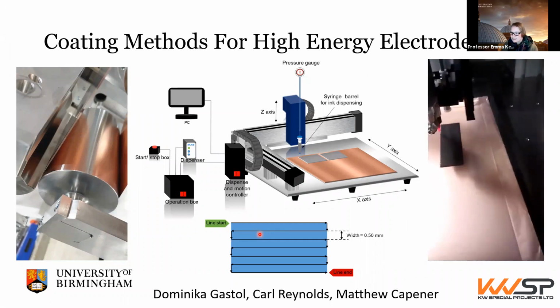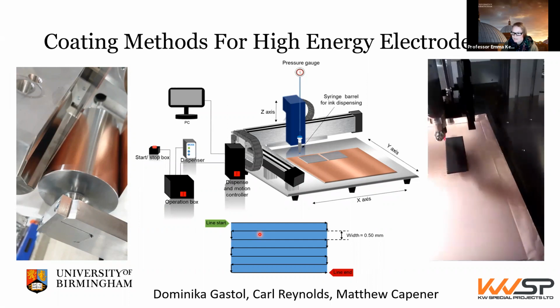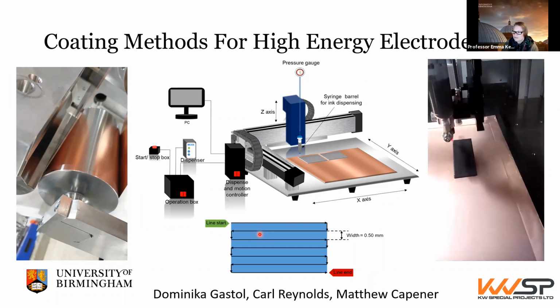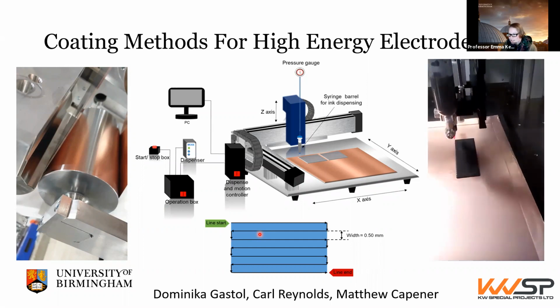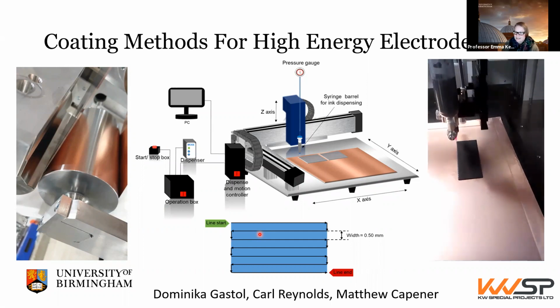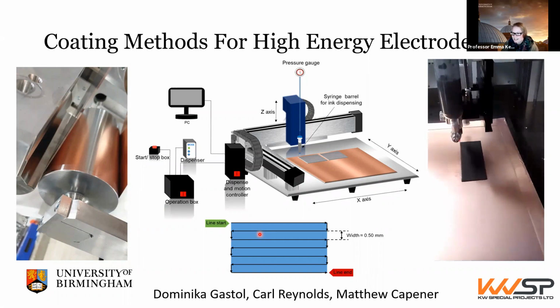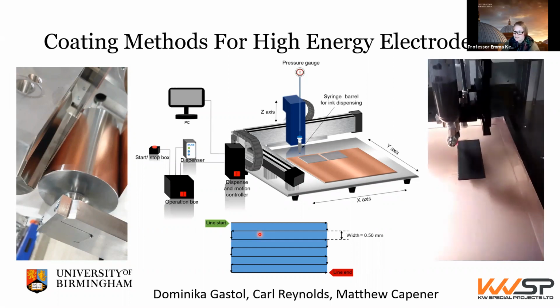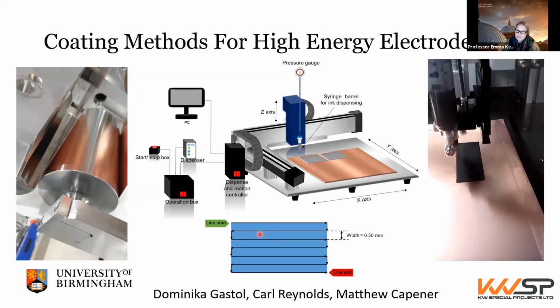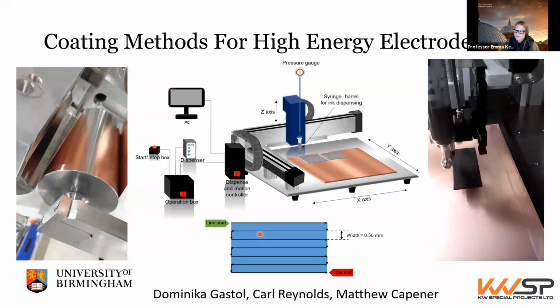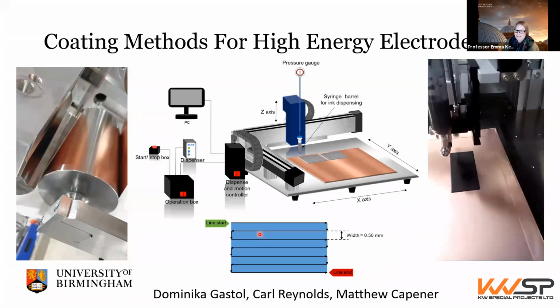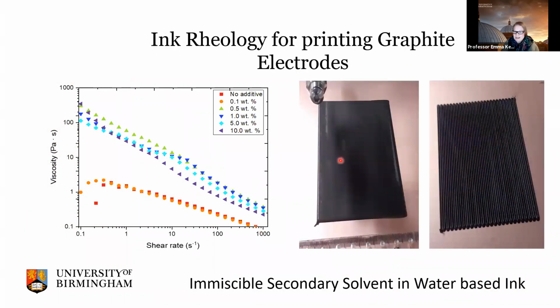And this is an example of how the slurry dispenser works. We have to optimize our ink to be able to extrude out of this machine, and then we can print different types of designs. This particular electrode that we're printing at the moment is a homogeneous cast, almost like a homogeneous electrode without any ridges in it. But we could also modify the inks so that we could create different slumping effects to either create these large flat electrodes here or these more structured electrodes that you see at the right hand side.